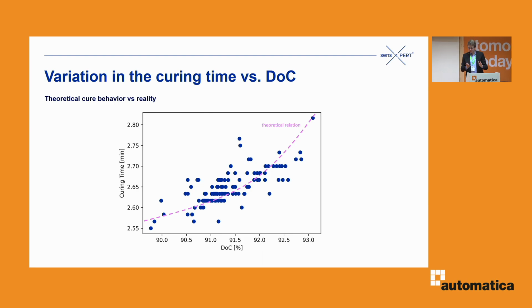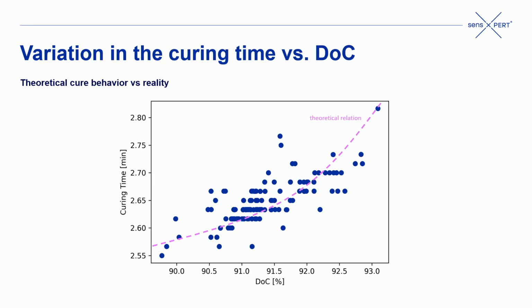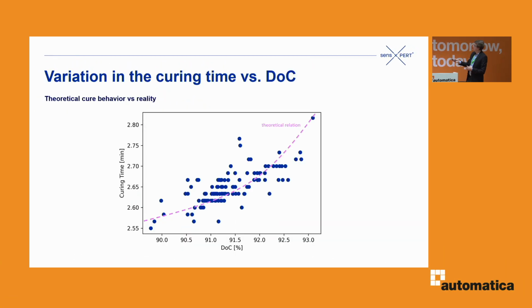And in this process that takes around 3 minutes, this is what we see. We have the curing time, which is the time that the part is subjected to the heat and production. And we have the final degree of cure that we determined in the laboratory. So we took those finished parts, did some laboratory tests, and determined the degree of cure. What you can see is that, first of all, we have a significant scatter in the degree of cure of the final parts. So the parts that we produce are going to have different properties. And the curing time is also a little bit different. That was the time from the minimum in this curing curve that we saw before to the demolding. So there's definitely potential for improvement here.